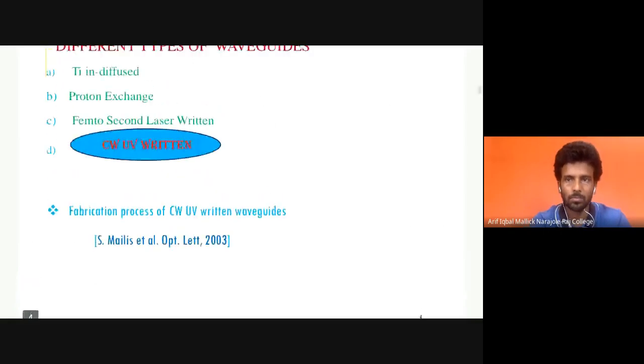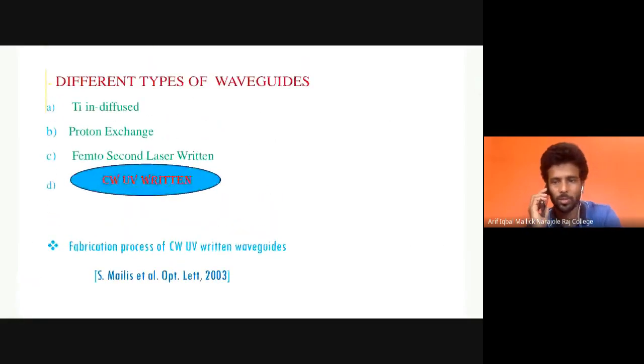There are different types of waveguides: titanium indiffusion, proton exchange, femtosecond laser writing, and continuous wave UV writing. We are interested in continuous wave UV writing due to its single-step process. Without lithography, we can fabricate it. After fabrication, the properties of the lithium niobate remain intact. It was first demonstrated by S. Mailis et al.